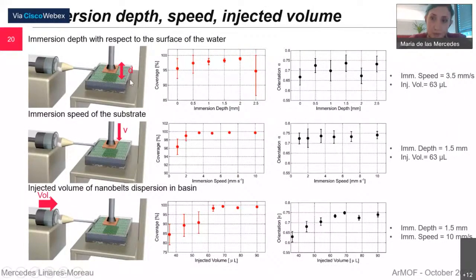Then we studied, with a perfectly leveled sample holder, the immersion depth. We were always comparing the coverage and the orientation because, in principle, we want to improve both, or find a parameter that has a compromise between the best coverage and the best orientation. We found in this case that for an immersion depth of 1.5 millimeters, we had the best orientation and very good coverage. Then we studied the immersion speed and we found a clear trend in the coverage, which improves with a higher speed. The higher speed also had the best reproducibility of this set, if we look at the error bars.